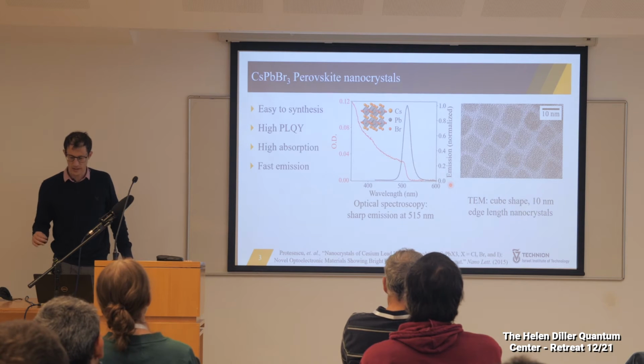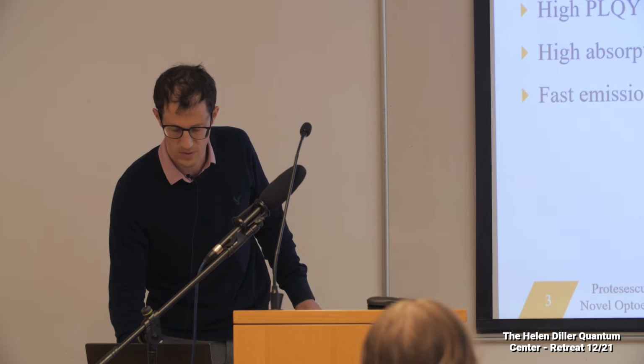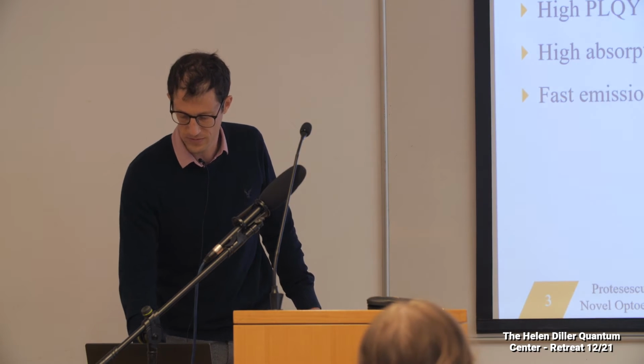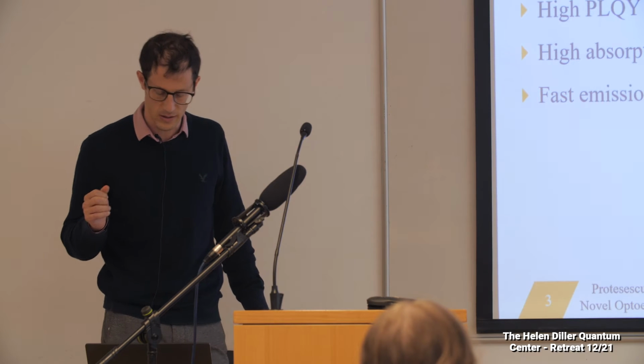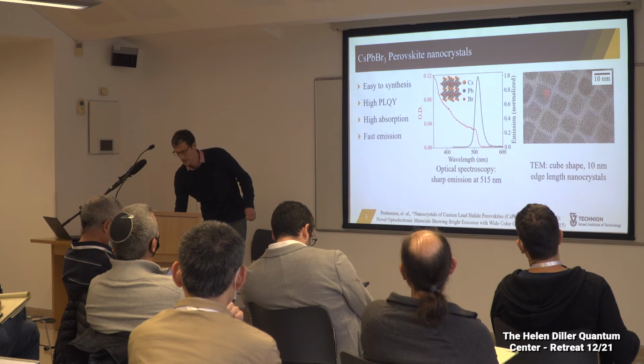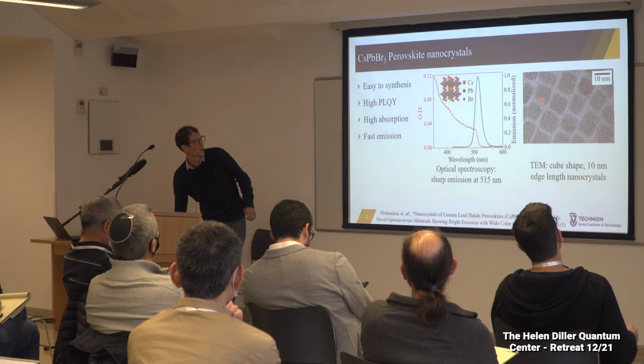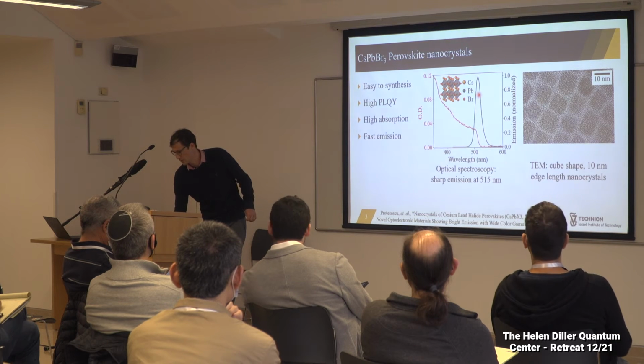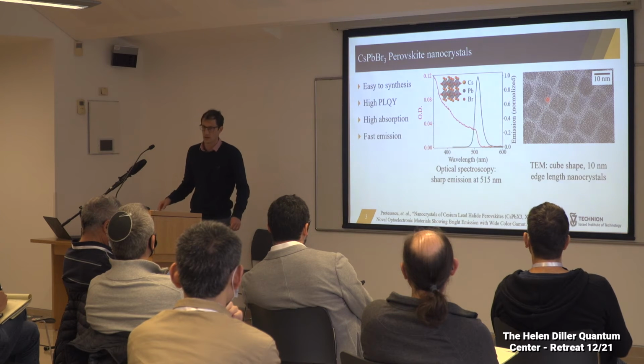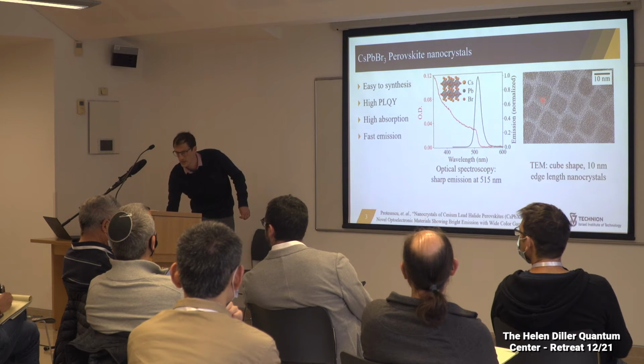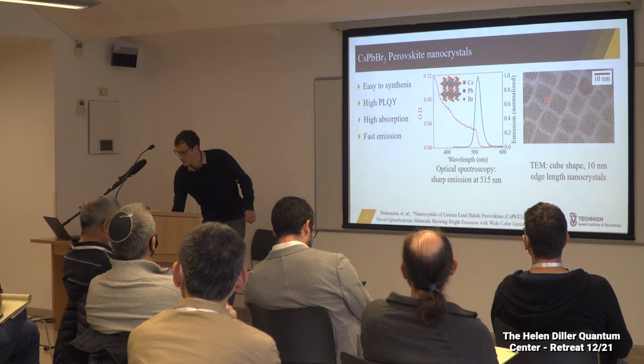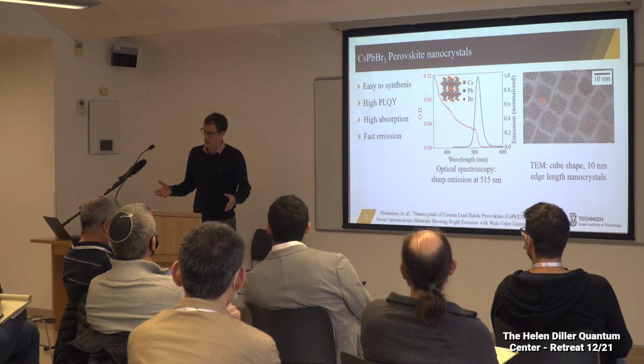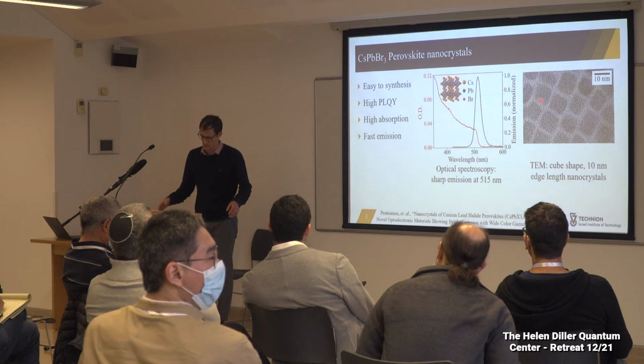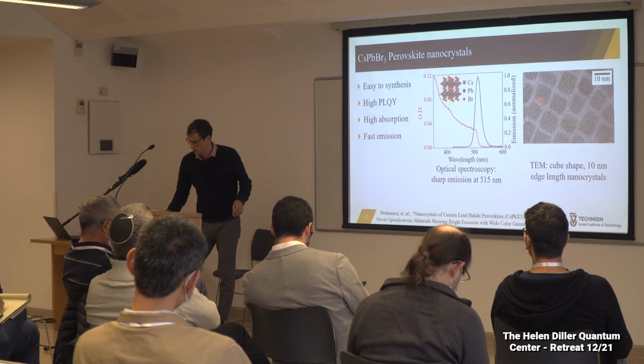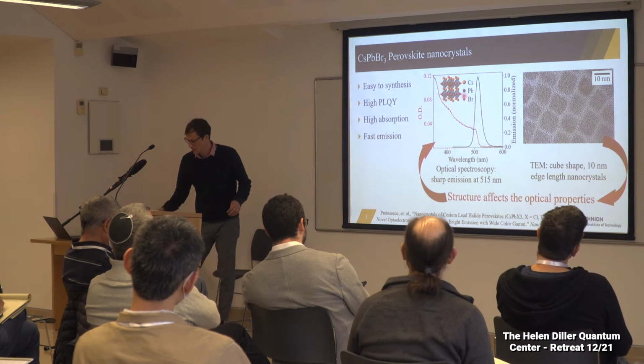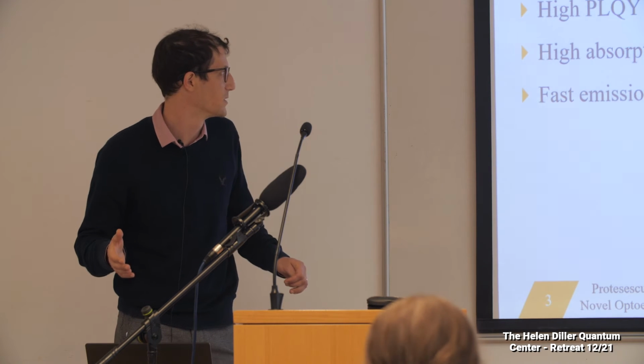So first, the material that we're using, cesium lead bromide, is a perovskite. It has a perovskite lattice. It was first synthesized as colloidal quantum dots by Protesescu and her colleagues in 2015, and the result is these 10 nanometer cubes. The emission is very sharp, around 515 nanometers, and when this little quantum dot is excited, an electron and hole are formed, and they are confined to this cube. This little region may increase the probability to recombine and to emit a photon, and therefore the high photoluminescence quantum yield. In general, this structure affects the optical properties of our material.